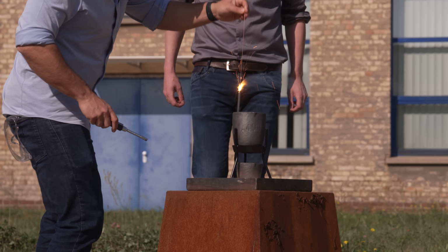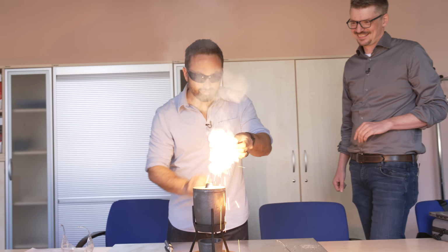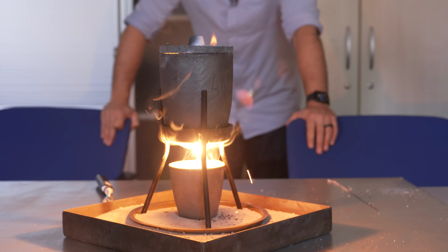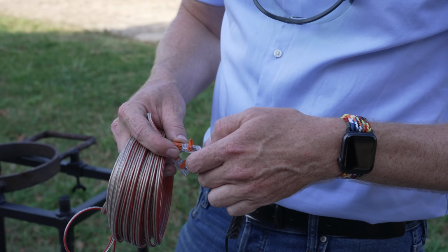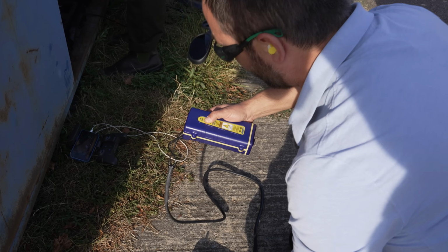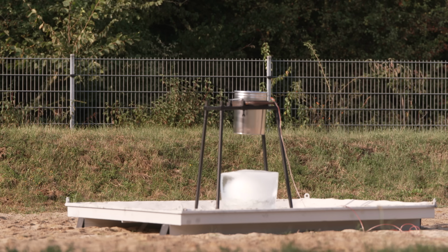This is why we've been using barium nitrate igniters, basically the same stuff that's in sparklers. It gets hot enough to break through the aluminum oxide layer and start the reaction. We want to make sure that the ignition temperature is so high that you can only light it deliberately. Because once it's going... I'm gonna push the button. In 3, 2. There is no way of stopping it.